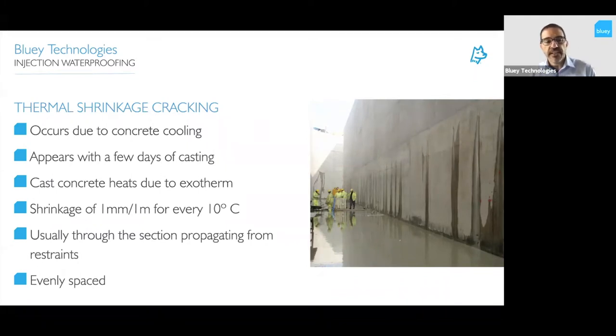And typically what you might see is about a millimeter per meter of shrinkage for every 10 degrees of cooling, which is quite a lot when you think about it. I mean, if you have a 20 meter long structure and it cools by 30 or 40 degrees, that's a lot of shrinkage that's occurring in that element, and a lot of cracking that needs to occur to actually release that tension. So as you can see here, the cracks are fairly evenly spaced because it just divides up that shrinkage over the length of the element. They usually propagate from the restraint, but they're usually through the structure. So that crack that you can see on the surface will be the same thickness all the way through, but it might be variable thickness as you go up the element. So they're the sorts of things to look for with thermal shrinkage cracking.